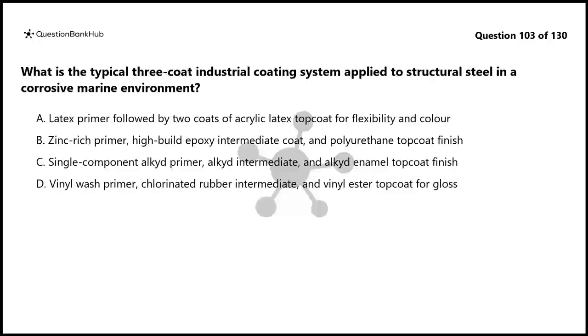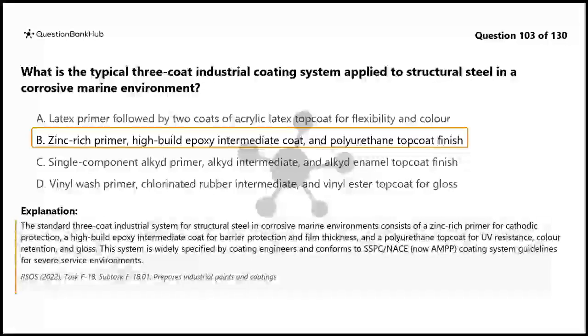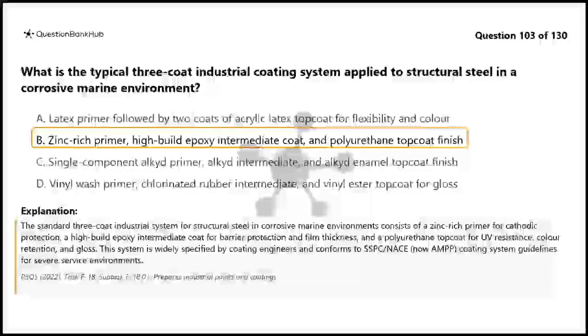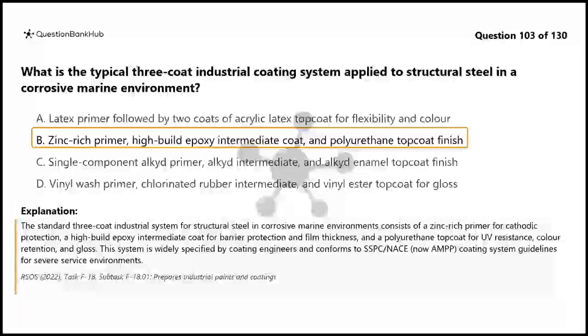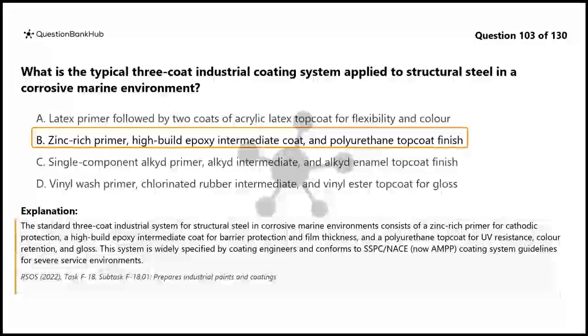The correct answer is B. The standard 3-coat industrial system for structural steel in corrosive marine environments consists of a zinc-rich primer for cathodic protection, a high-build epoxy intermediate coat for barrier protection and film thickness, and a polyurethane topcoat for UV resistance, color retention, and gloss. This system is widely specified by coating engineers and conforms to SSPC/NACE, now AMPP, coating system guidelines for severe service environments.